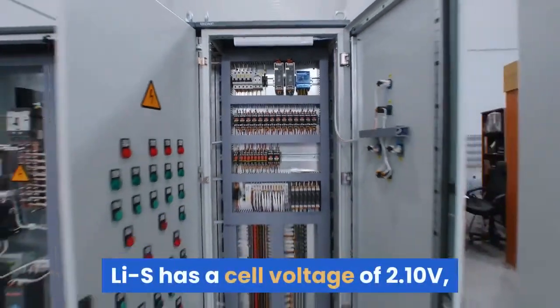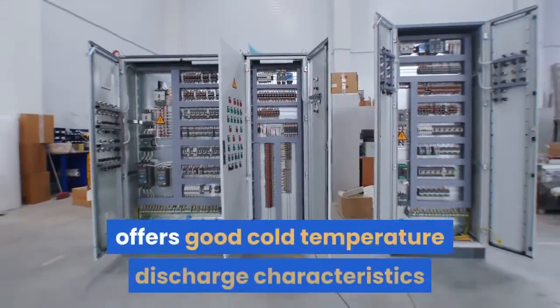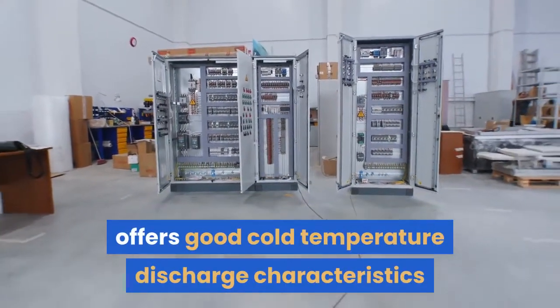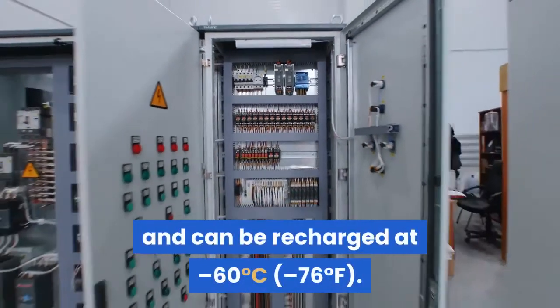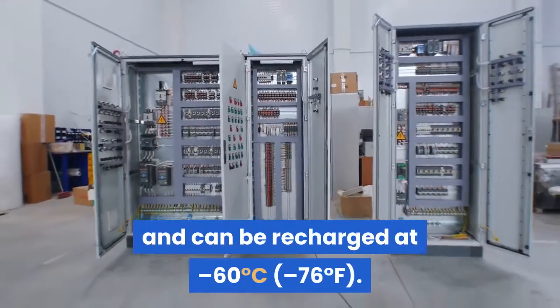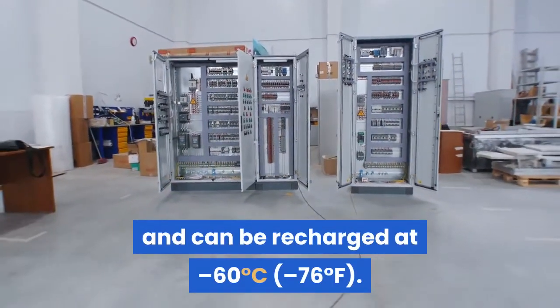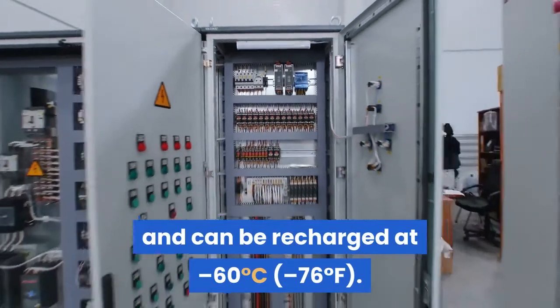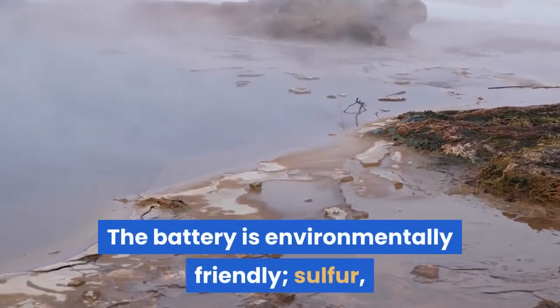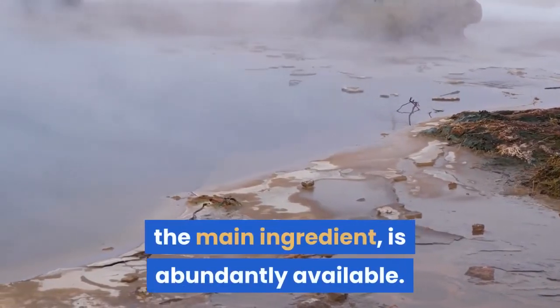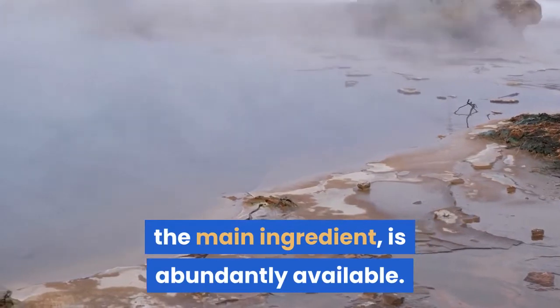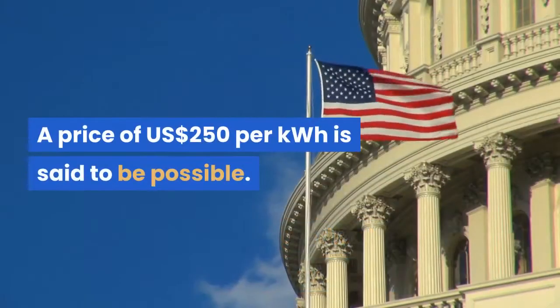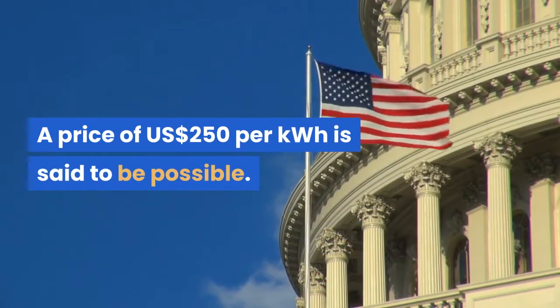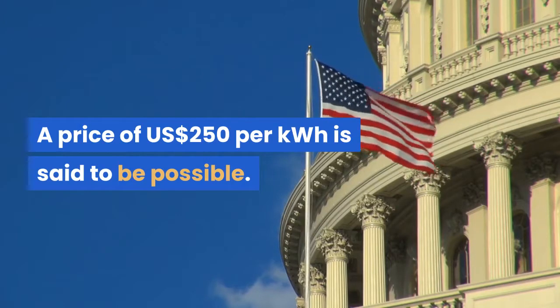Li-S has a cell voltage of 2.10 volts, offers good cold temperature discharge characteristics and can be recharged at -60 degrees Celsius, -76 degrees Fahrenheit. The battery is environmentally friendly. Sulfur, the main ingredient, is abundantly available. A price of $250 per kilowatt-hour is said to be possible.